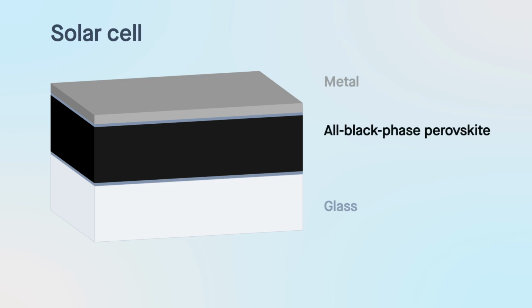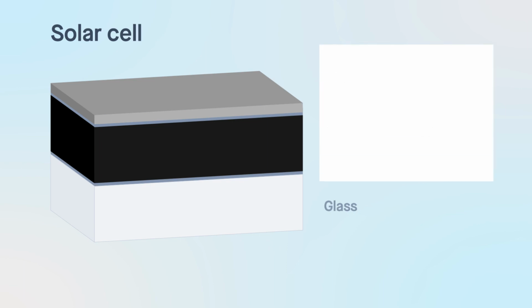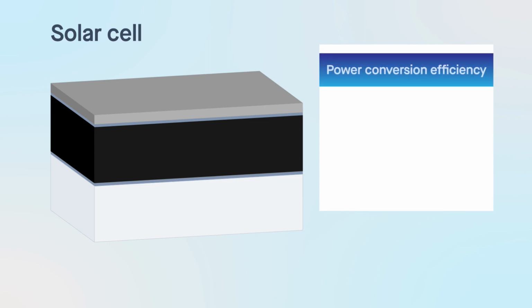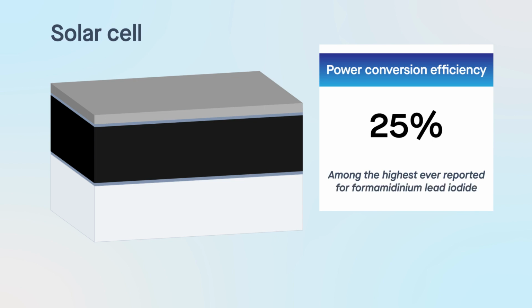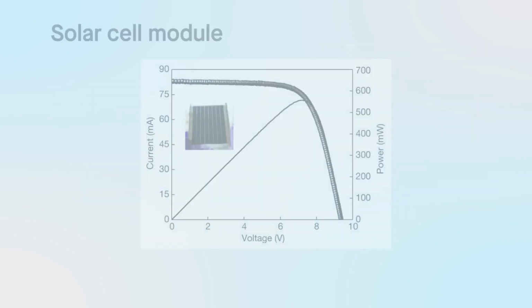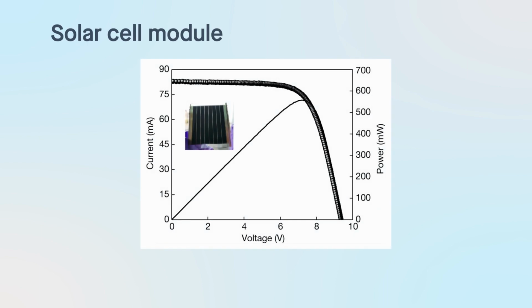When packaged into a solar cell device, the all-black phase perovskite outperformed all solar cells in its class, reaching a power conversion efficiency of 25%, among the highest ever reported for formamidinium lead iodide. Larger solar modules were also constructed. The efficiency of these devices is the highest reported for perovskite solar modules, demonstrating the scalability of the new material.